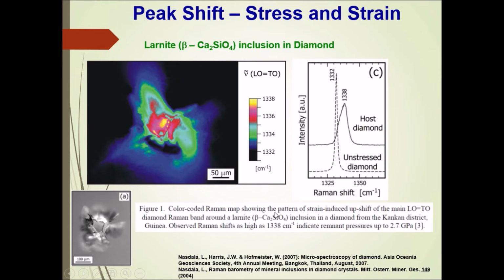Again, we can detect any change in the crystal structure for the same sample. Like if we apply extreme conditions on the sample, like pressure or temperature, for sure we have the same crystal structure, but we have, for example, some stress on the crystal structure. So we can easily distinguish between unstressed sample and stressed sample in this kind of crystals, so we can find any change due to any external physical property like pressure or temperature.